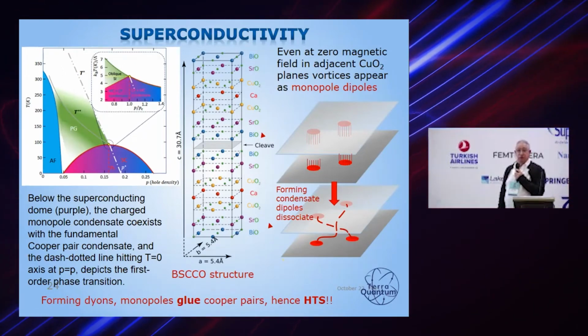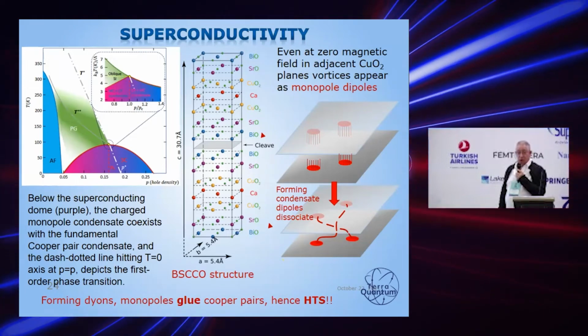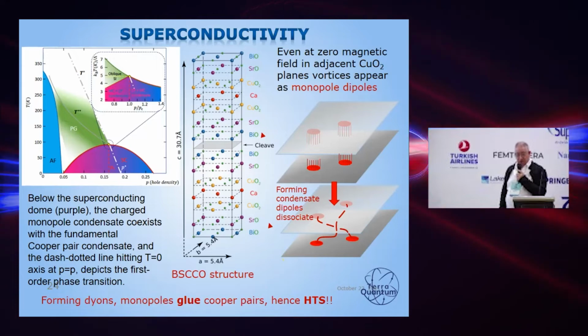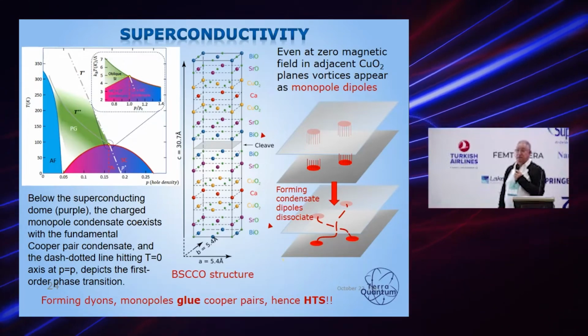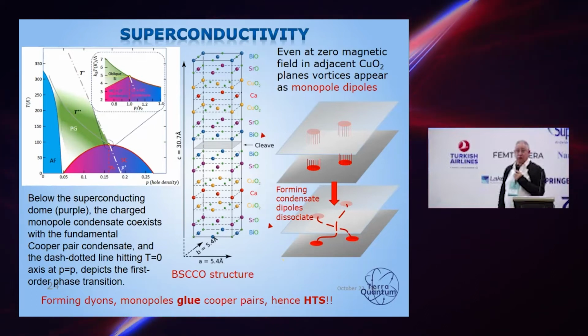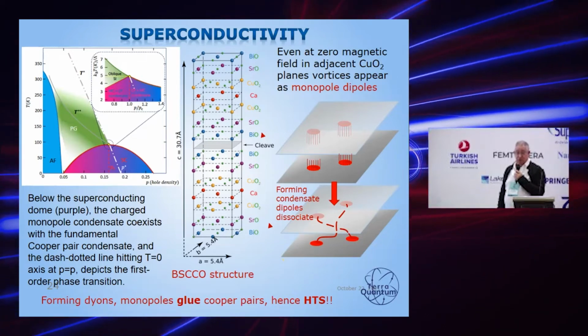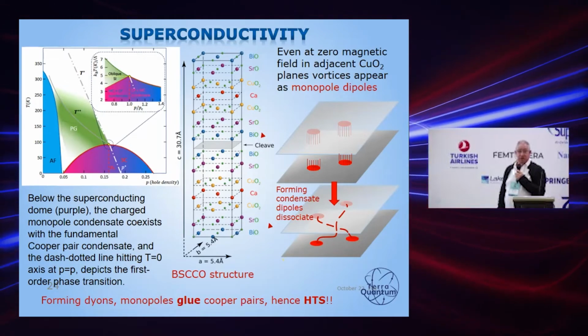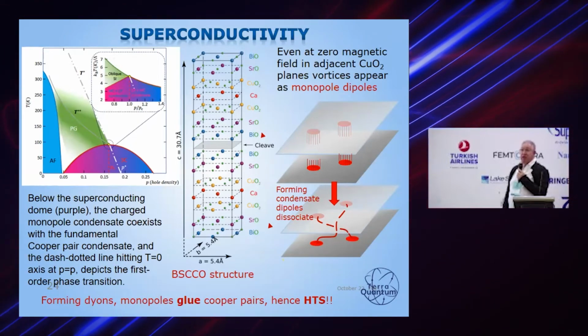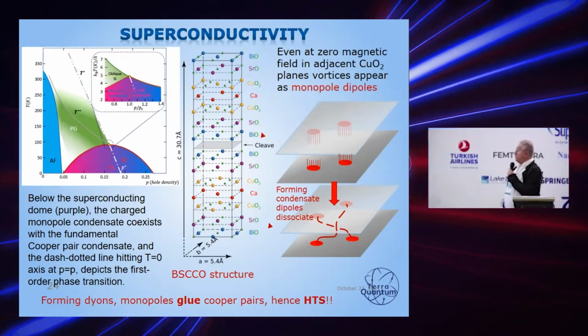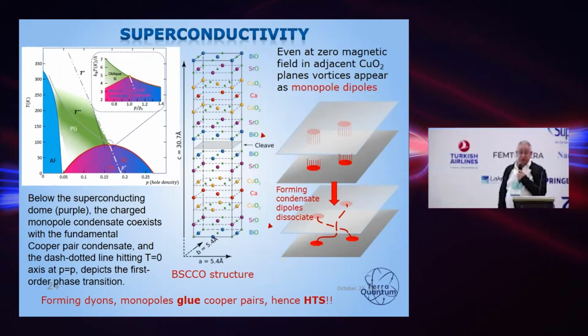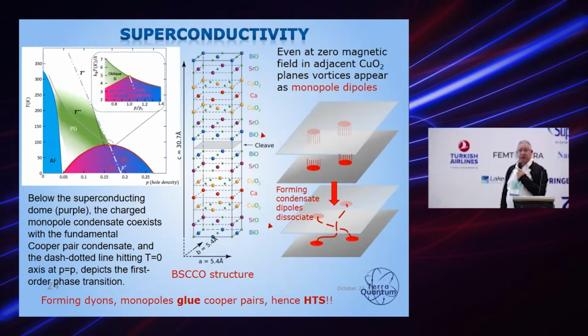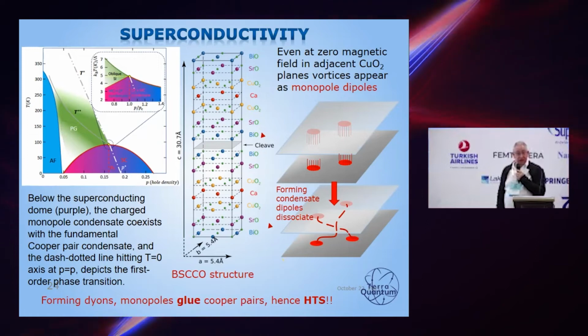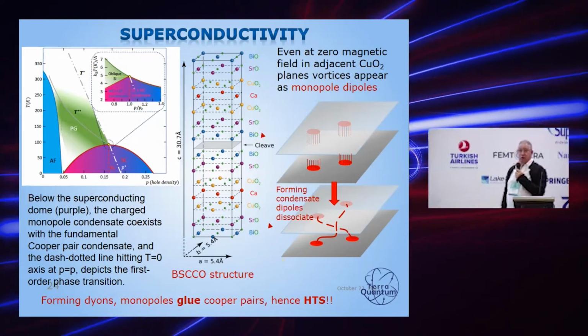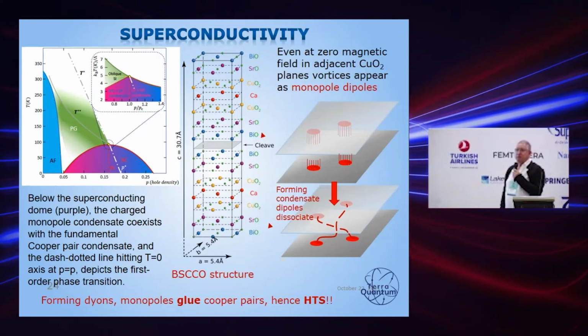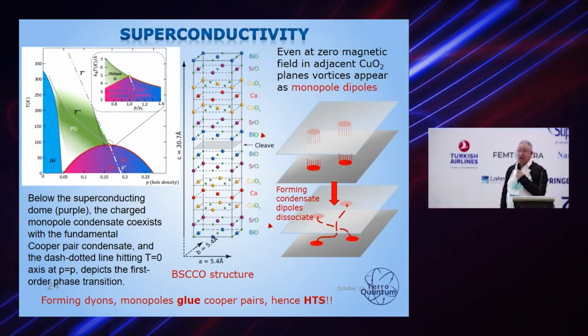And then, of course, we immediately understand why in the underdoped region we have these Cooper pairs which go well above the superconducting transition temperature, because they go there as dyons. And then this model or this description describes another remarkable thing. We know pretty well that if we take a single layer, for example, of BSCCO containing one unit cell, then it's going to show practically the same superconducting transition temperature as the bulk sample.